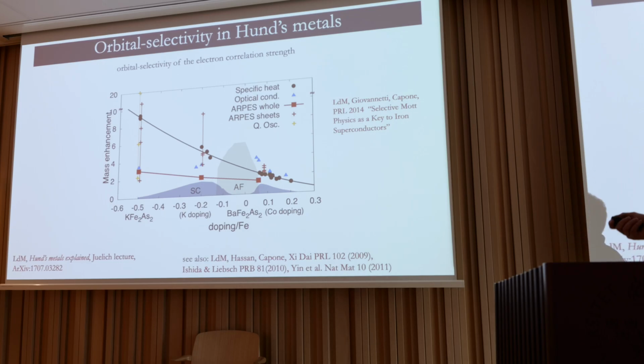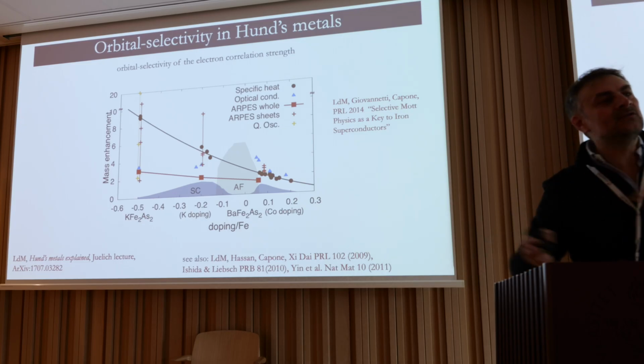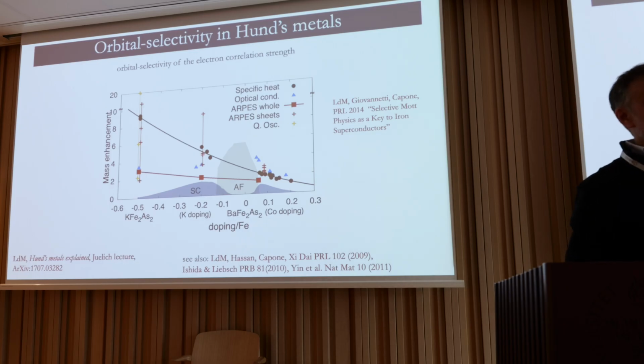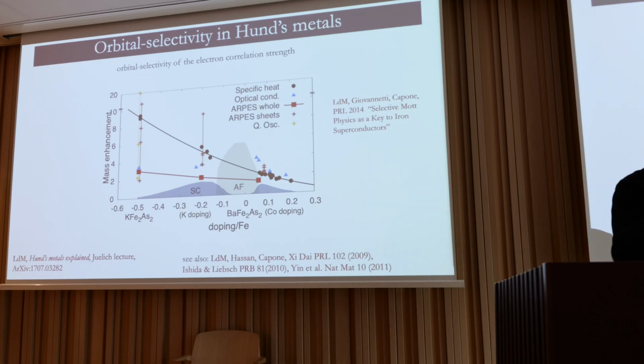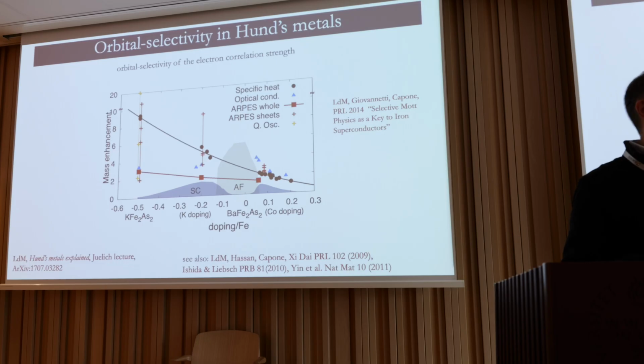If you look at ARPES or quantum oscillations that resolve sheet by sheet at the Fermi level, you see that estimates of the Fermi velocities, or direct estimates of the masses resolved sheet by sheet, are all concentrated like these red crosses if you're on the electron doped side, and they spread more and more if you go to the hole doped side. So with the increase of correlations, the selective nature of these correlations also increases, and you have heavy electrons coexisting with light electrons, exactly the situation we know from heavy fermions.